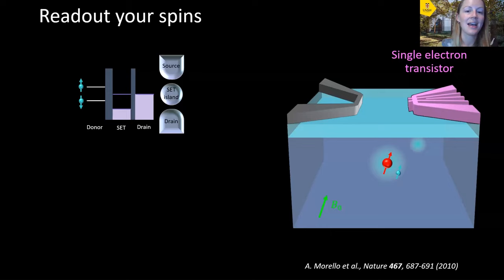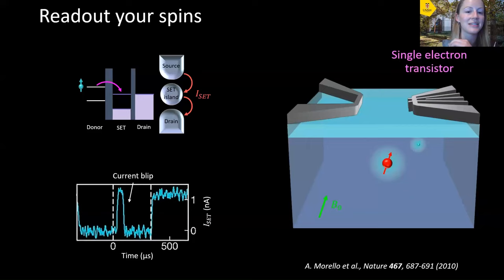And so to operate this system in readout, we first tune the Fermi level of this SET island to lie in between the spin up and spin down states of our donor electron. And so if the electron is a spin up, it will have a high enough energy to tunnel off the donor and onto the single electron transistor island. And this causes the donor to become ionized and have a relative positive charge as it's lost an electron.